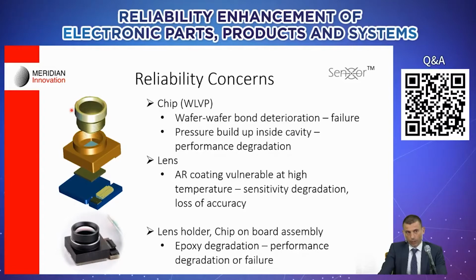Then you have a lens which is not an ordinary glass, but a germanium material which is transmissive to infrared radiation, and otherwise it's opaque to visual light. Glass, for example, or typical optical lenses for visual light are not suitable. The transmissivity, however, depends on the so-called anti-reflective coating, which improves the transmissivity by a factor of about 40%. And it is quite sensitive to high temperature. And finally, the chip and lens holder are bonded to the PCBA by epoxy, which has its own challenges and degradation over time that could lead either to failure or just a degraded thermal conduction path.